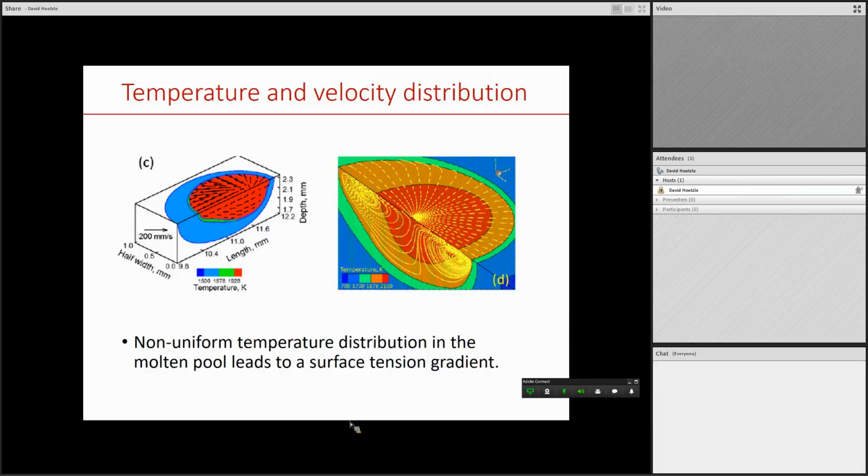But those take an incredibly long amount of time to compute. So if you want to run that simulation, they do really small domains, just on the order of around a millimeter in size, a millimeter cubed, and even smaller than that. It takes, I think, 400,000 to 700,000 CPU hours to compute. So you have to have access to supercomputers like Lawrence Livermore National Labs does to really do that.